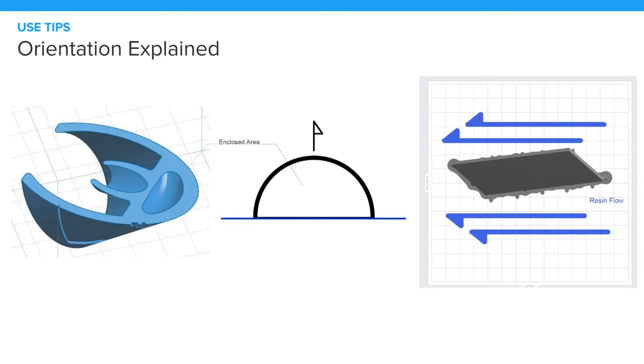On the far right, what we're trying to communicate here is that all long parts should be oriented so that the long side is parallel with the front of the machine. The reason for this is it's reducing the stress on the part caused by the peel operation, and it's allowing the resin to flow more easily around the part. This is especially important if you're using a Form 1 or a 1+, because the lever action creates a downhill movement of the resin, and it's really critical that you follow this rule.